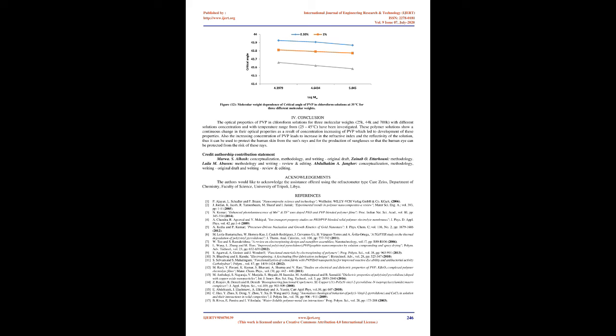The critical angle values decrease linearly with the increase of the concentration for 3 different molecular weights at a selected 35°C as an example, as shown in figure 10, because it is inversely proportional to the refractive index. It is clear that as concentration increases, the density also increases and causes the critical angle to decrease, and this is in agreement with 25. 4.2 Temperature effect.